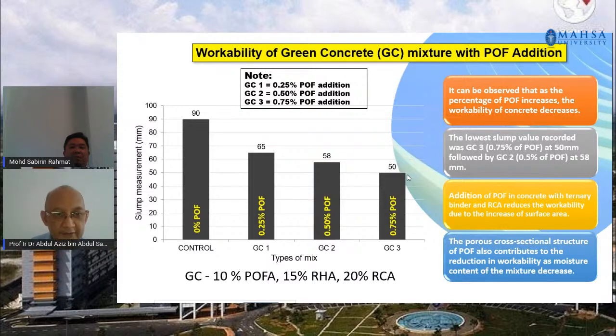The first is the workability study of the green concrete mix with various percentages of palm oil fiber. Okay, as you can see there, GC1 at 0.25%, GC2 at 0.5%, and GC3 at 0.75% of palm oil fiber. At 0% palm oil fiber, this is the green concrete without fiber, and we achieve 90 millimeters of workability. But when we add the fibers at the various percentages, the workability drops down to between 65 and 50 millimeters. Okay, it gets stiffer as we add more fiber in this concrete mix.